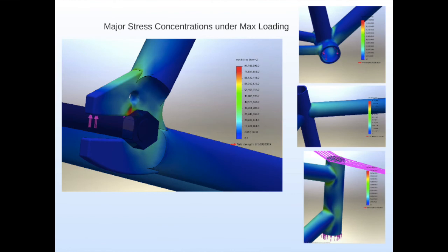This way we could take a frame and look at where its greatest stress concentrations would form. Using the analysis, we could conclude that it would be able to conform to our constraints such as a 3000 Newton impact and being able to withstand this load for 10^7 cycles. The major stress concentration showed up around the head tube, seat tube, and bottom bracket. However, the maximum stress that was experienced was seen in the rear triangle.